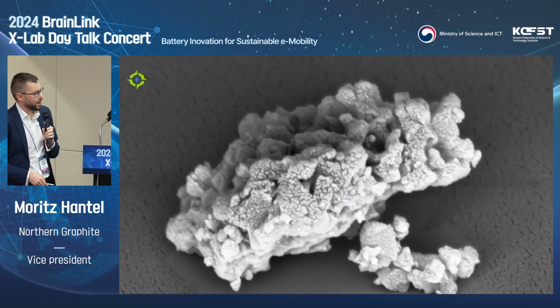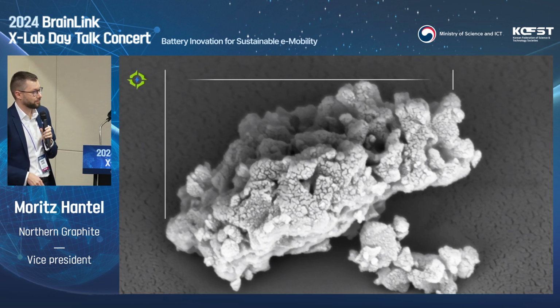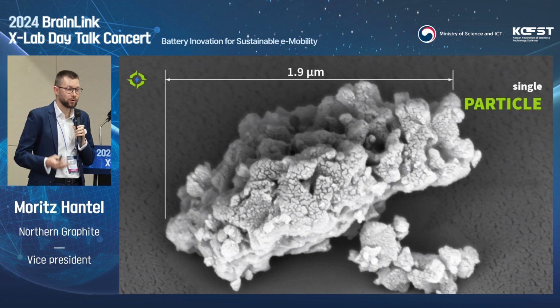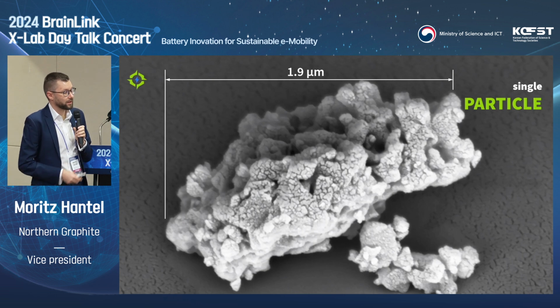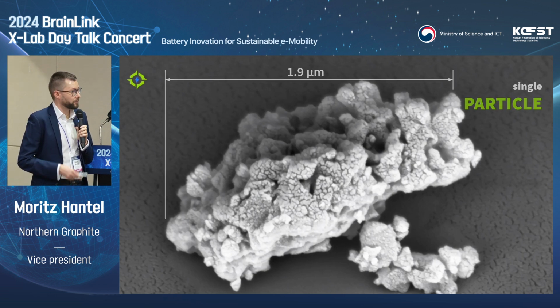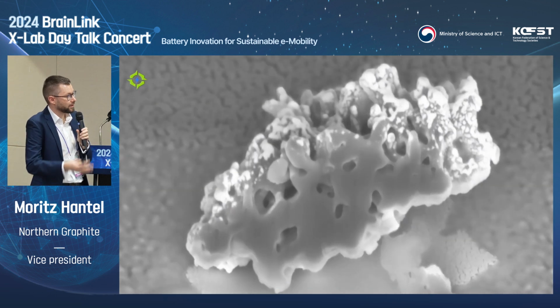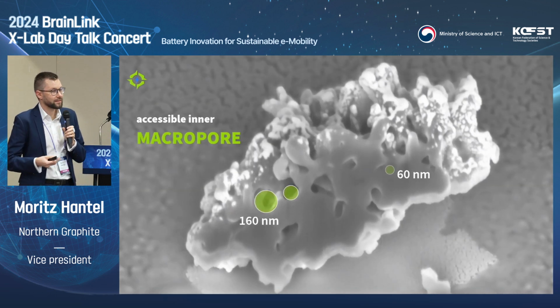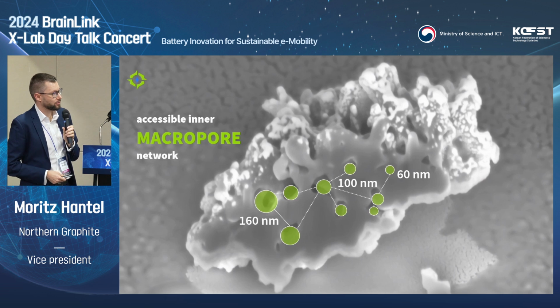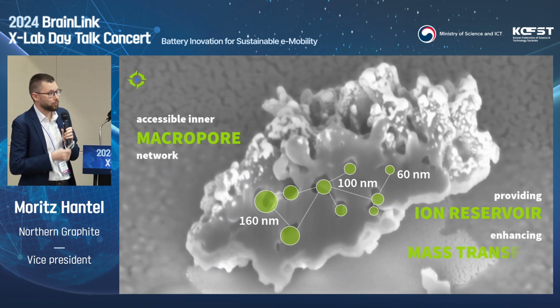So let's have a look at how this looks in reality, because one special thing is that it's a single particle. The material does not come as an agglomerate, but as single particles, and in this example, we have a particle of around 2 micrometers. If we apply a focused ion beam, we can cut this particle open, and what you then reveal is the inner morphology, the inner structure of the material, where we have open pores, and because it's a synthetic system, we can tune this pore network and also the size of the pores to a certain degree required for the application.